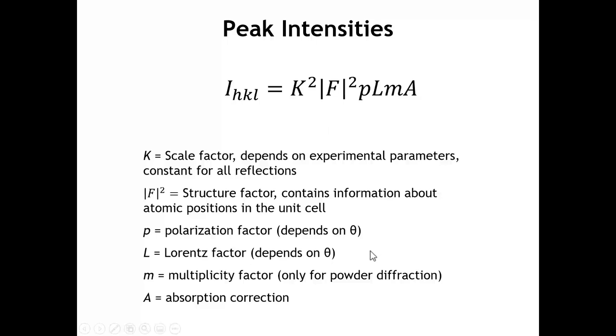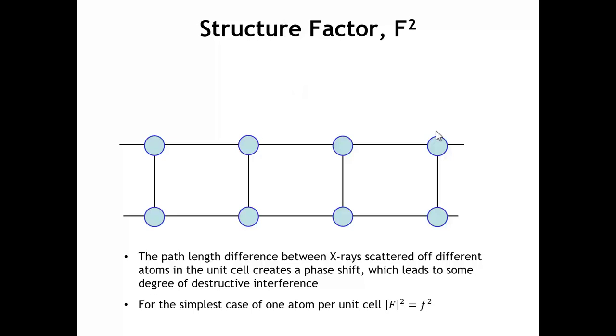P and L are the polarization and Lorentz factors — both are theta-dependent. We'll talk about those more in a minute. Then we have M, the multiplicity factor, which is something we have to deal with in powder diffraction experiments but not in single crystal diffraction experiments. And finally, we have what's called an absorption correction. Most matter is highly absorbing for X-rays, and as X-rays travel through the sample and are absorbed, that impacts our peak intensities.